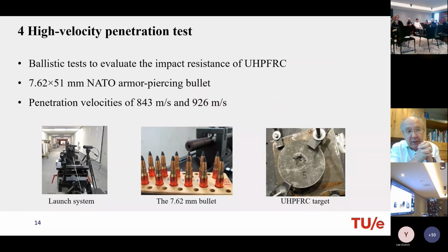Then we looked at the impact number and the absorbed energy before the material collapses. As the last test, we did a high velocity penetration test. We did it at the end because we have limited access to these tests. Of course, we only had a few days or perhaps a week in total. And it was not in our own lab. This was done by the Dutch Army.